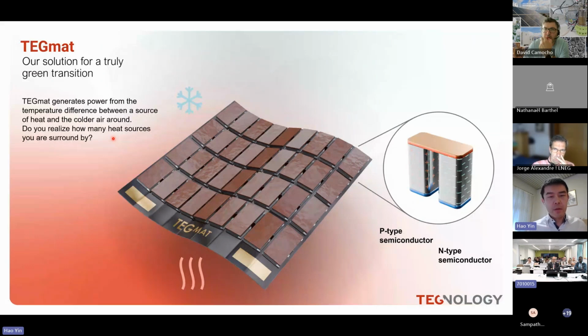having a flexible TEG. First of all, it's much easier and more robust to apply it on non-flat surfaces. So the adhesion to the heat source becomes much easier. And also the thickness of our substrates is much thinner than ceramics, which also makes the heat exchange rate a bit higher. And this design is not specific to any material because it's flexible. It doesn't require a high match of the thermal expansion. That means we can, in principle, build different materials into a single module so they can expand at their own pace. So the substrate can absorb this expansion.